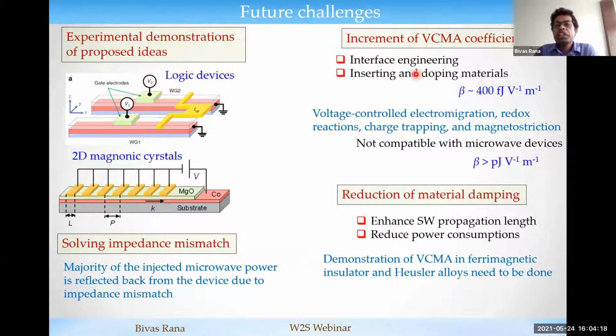Also, we need to increase the VCMA coefficient to more than a picojoule per volt per meter. And the most important thing is the reduction of the material damping parameter, because in order to utilize VCMA, which is an interfacial effect, we need to reduce the thickness of the ferromagnetic layer, and that essentially increases the damping constant.